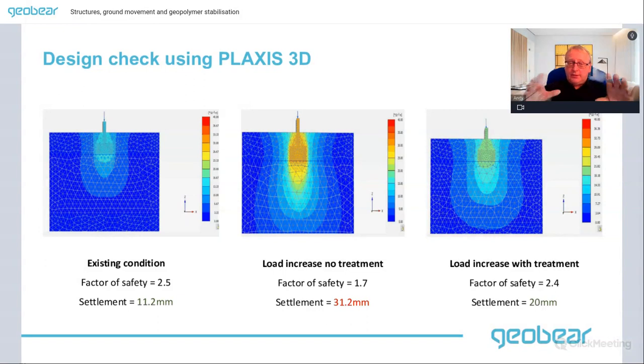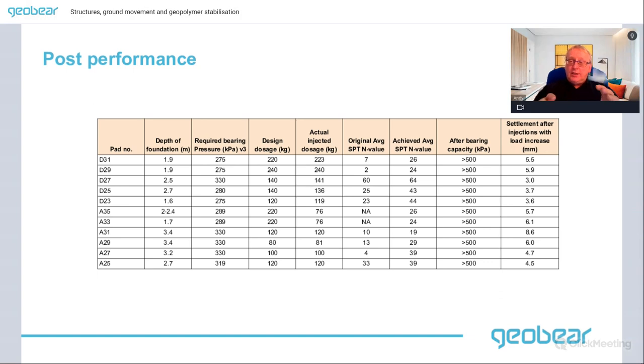We ran checks using Plaxis as a before and after to see what we could achieve in terms of increased bearing, and what the performance would be. And checking our design with Heathrow, it looked like we could achieve what they were aiming for. And then we actually did some, these are the after results. You may not be able to read this, but the required bearing pressures were of the order of 270 to 330 kilonewtons per meter squared, quite an increase from the existing 160. And after our injections, all pad foundations had an increase in bearing capacity to more than 500 kilonewtons per meter squared. We far exceeded the required performance.